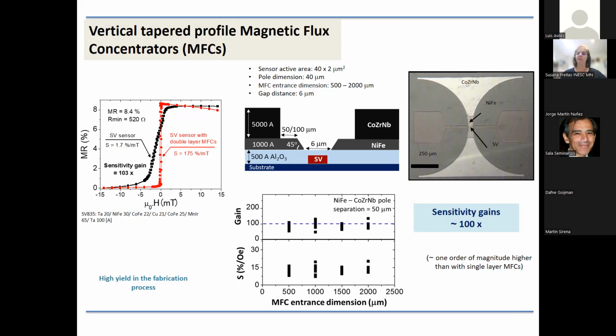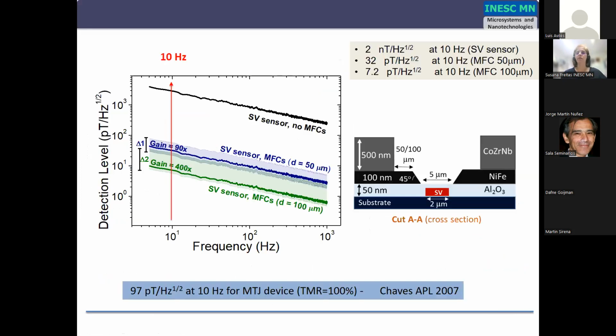However, if you can increase your sensitivity by a factor of 100, which is what we see here, gains of 100 times in sensitivity, then it's worthwhile to sacrifice a little bit the space. And this is what we see here in more complex structures. And we have here less than 100 picotesla measured for one TMR device. And here we can compare with 7 picotesla with a spin valve device integrating a complex structure for focusing and refocusing the field in the sensor region.